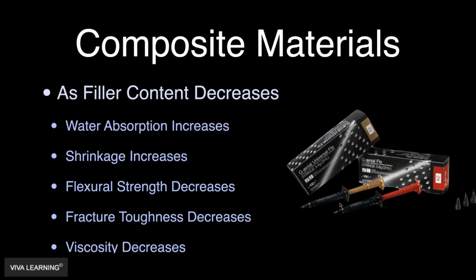the filler that tells us basically about the physical properties and the handling properties. So as you decrease the filler content, so the material is a much higher proportion of resin or monomer, pretty much all of the physical properties get worse, less desirable. So water absorption increases, shrinkage increases, flexural strength decreases, fracture toughness decreases, so it becomes more fracture prone.